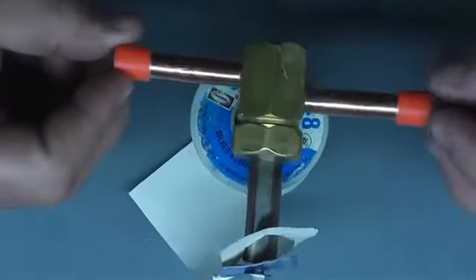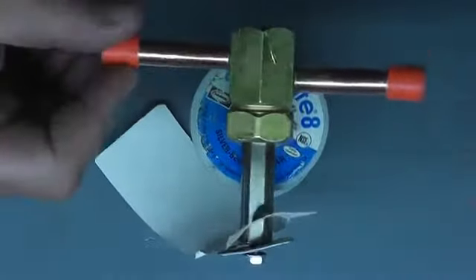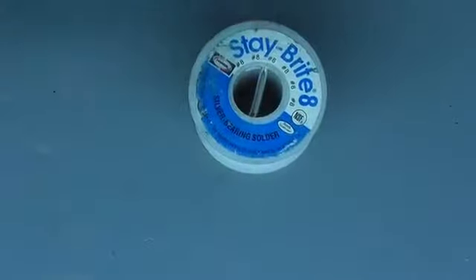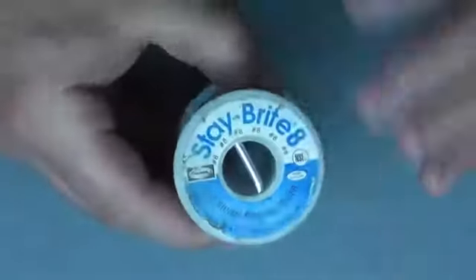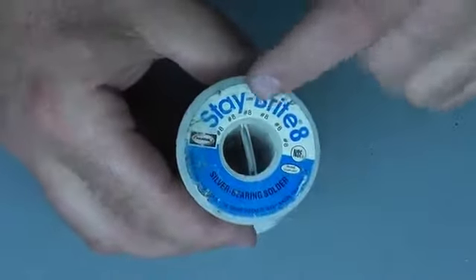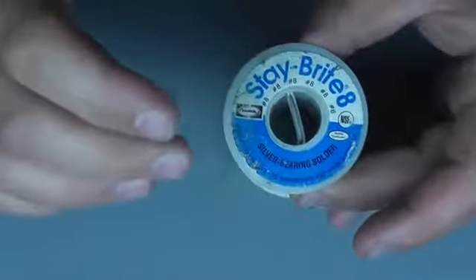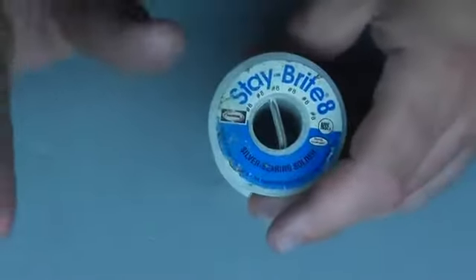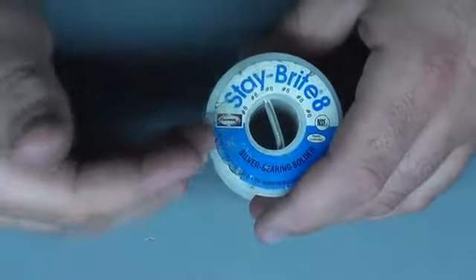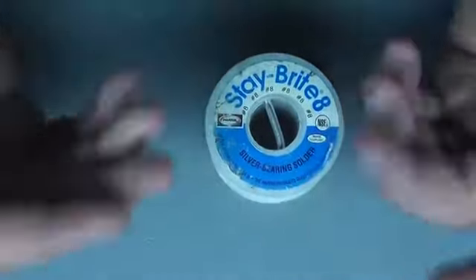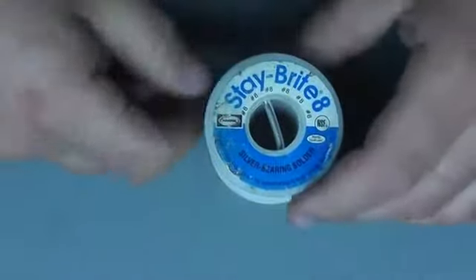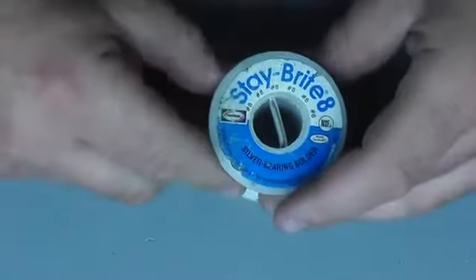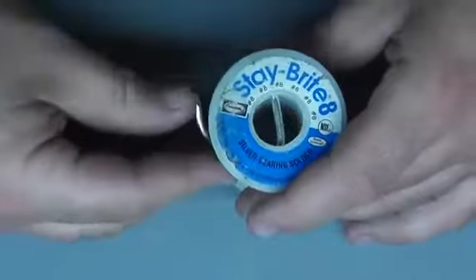But you're only heating these two joints here to 400 degrees instead of 1500 degrees by using soft solder. So this is a very, very good product, and it has a lot of benefits and not much detriment. I think, like I said, the reason why people braze is because you don't need to clean. There's no joint prep. You just put the pipe together, braze it. People think that they're saving time, and people don't like to clean the copper.